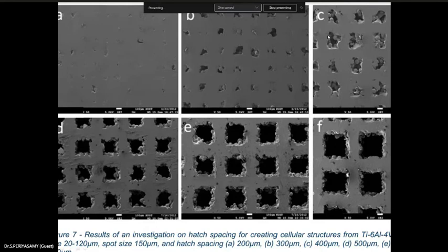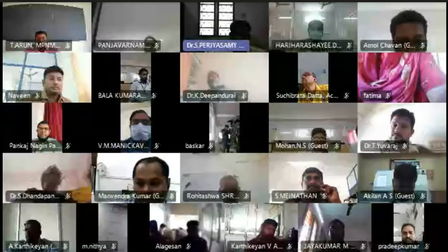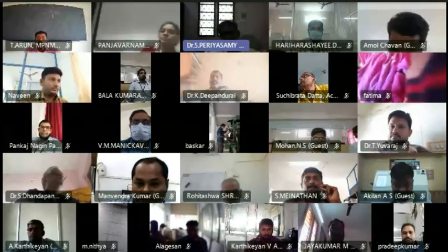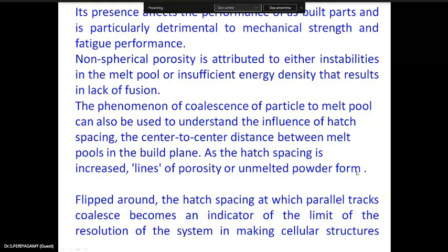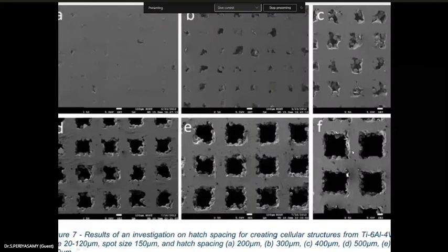The porosity can form as large irregular pores due to lack of melting, or shrinkage micropores due to lack of feeding. The small micropores will shrink once the feed rate differs or varies within the inter-dendritic zones.